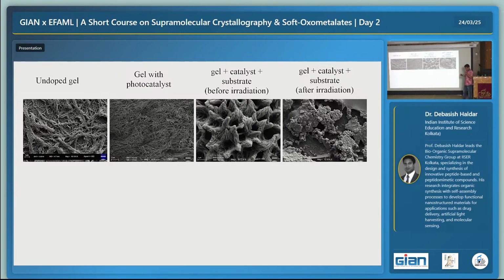That means once the gel melted, basically our reagents are exposed to the air, and by that time oxygen is killing the reaction, and so we are stopping at 68% product. But if we can protect it, maybe with some other gelator, or maybe with a high concentration of gel, the reaction can go up to 90-95% yield, because in solution state the oxygen will intervene and it will kill the activation state, and it will stop the reaction.